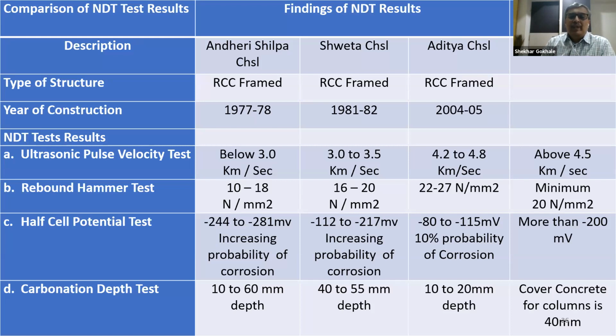So the 1977 building gave ultrasonic results below 3, Shweta gave 3 to 3.5, and Aditya gave 4.2 to 4.8. Normally, UPV above 4.5 kilometer per second is excellent quality concrete. So in the case of Aditya building, 2004-5, which is a comparatively new building, we got the best results. And for the 1977-78 building, we got results lower than 3, which is poor quality concrete.